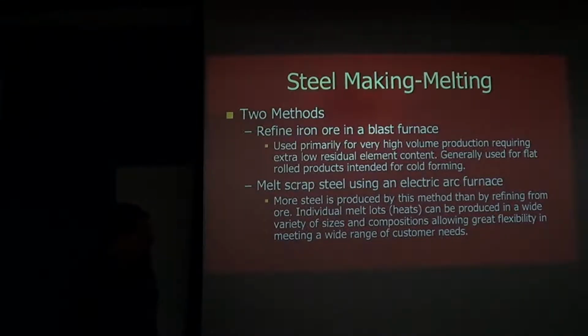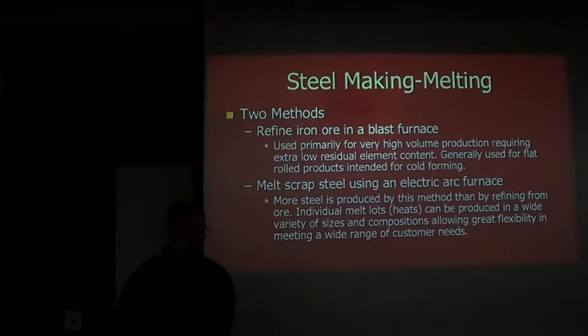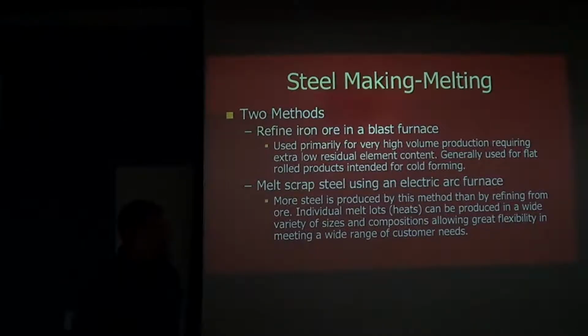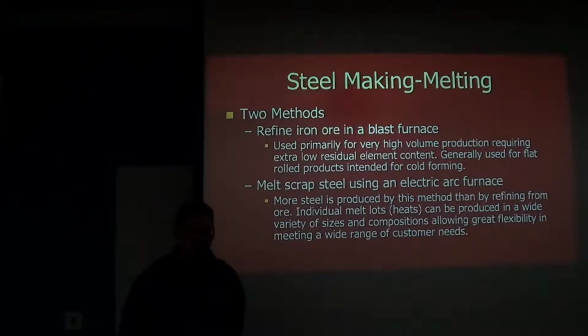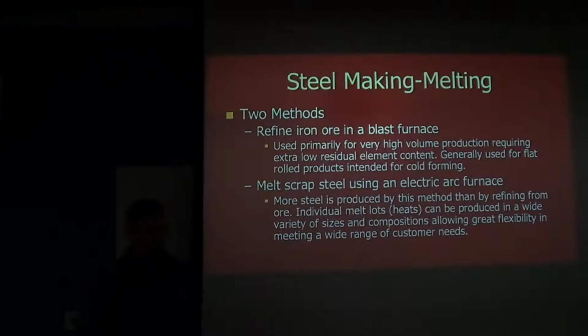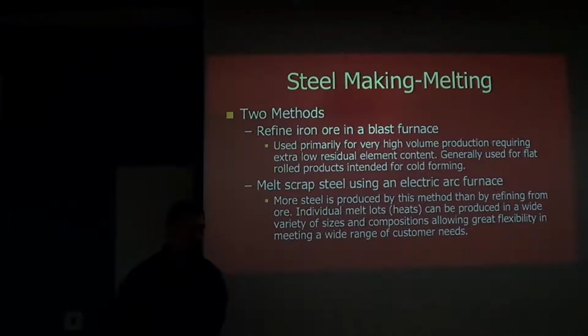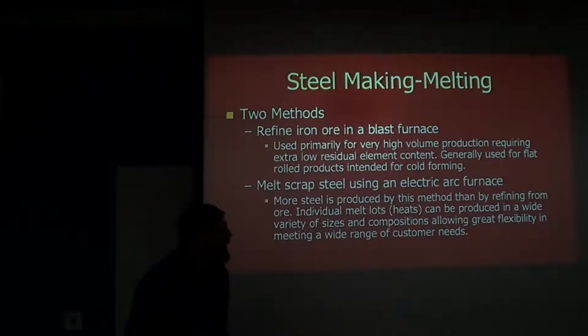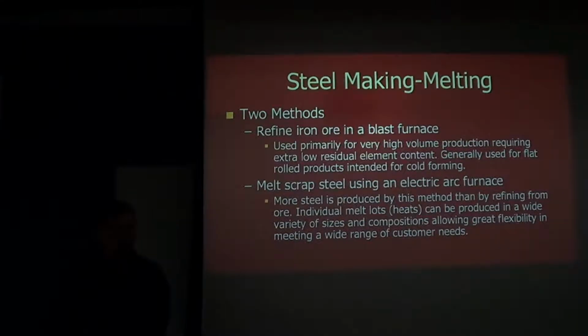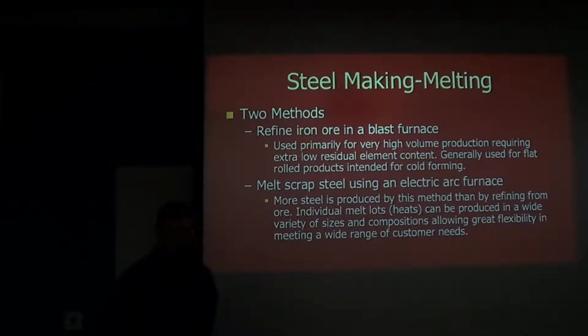As you look at what's going on within the stack, you're getting carbon from the coke, which is basically sort of pre-burned coal. The carbon is being absorbed by the iron ore and is reacting with the oxygen. You're pulling the oxygen off, and you're being left with iron. But the iron is now absorbing excess carbon, so you get a very high carbon, essentially cast iron. And all of this liquid metal is trickling down through this big tower and collecting at the bottom.